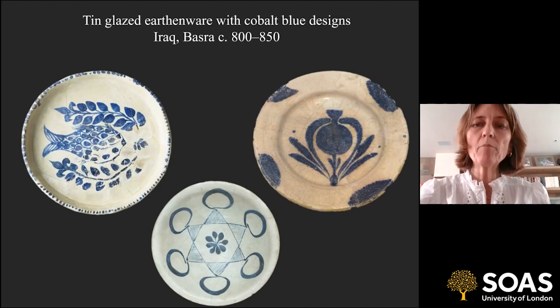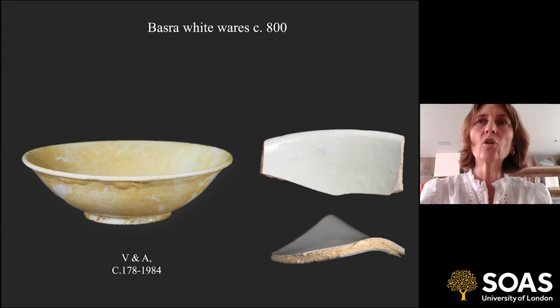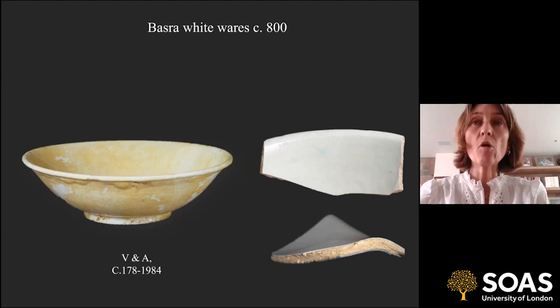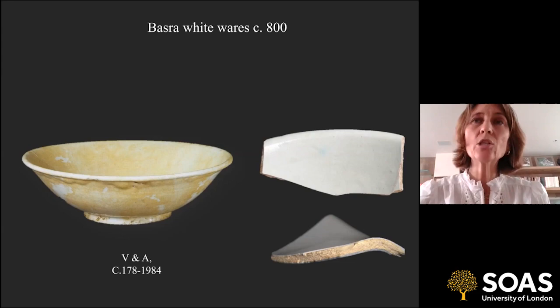They come up with the idea of making earthenwares. To get blue on white, you first need white — but the local clay is a nice yellow color, not the blue-on-white contrast they're looking for. So they experiment with local technologies including alkali and lime combinations, but the formula they settle on — which will spread across the whole Mediterranean over succeeding centuries — is tin glaze: a lead-fluxed glaze with finely crushed tin added, whose particles sit within the glaze and give a very nice opaque white surface.